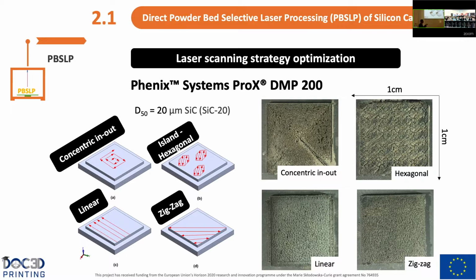Here, each time the laser arrives at the end, when it's turned on, there is a decrease in the temperature. We are not able to reach the sintering temperature of silicon carbide, and there is bad adhesion between the layers.